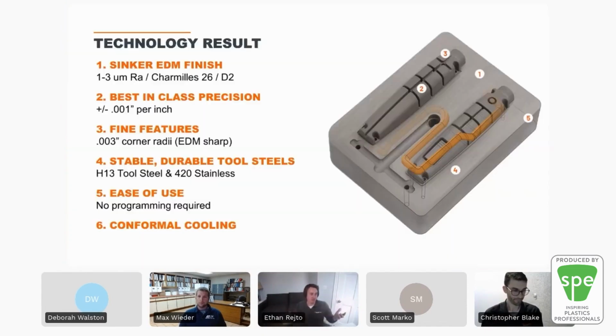But what really matters is the result here. We say we get you essentially a Sinker EDM finish, Charmilles 26, D2, sort of a matte finish on the part. Of course, if you want to polish it, you can do that afterwards. Tolerances of about 1 thou per inch. So on a 3-inch part, you'd be about plus or minus 3 thou.